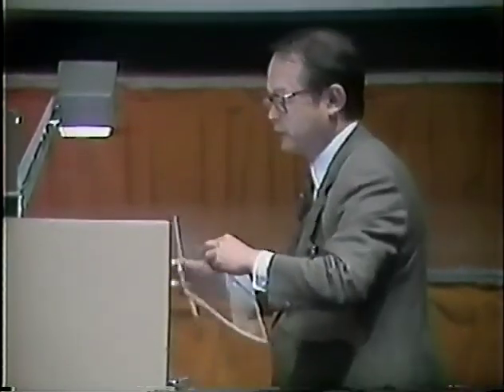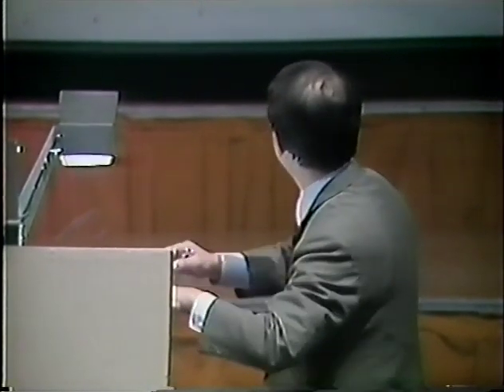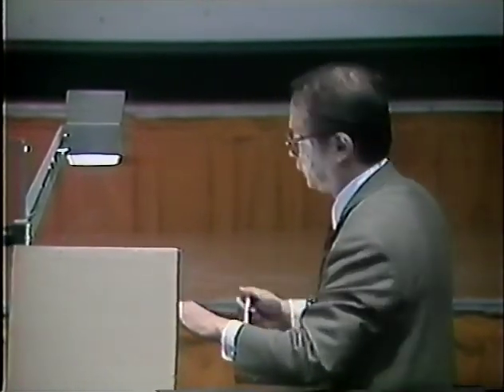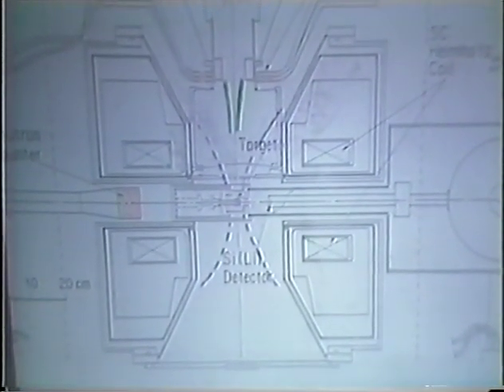At the end of the muon channel, we installed this setup. The muon is coming to the target area. At this moment, it's written on the D2T2 target, but it will be replaced by the palladium deuterium system. And we placed all the target under a high longitudinal magnetic field of 3.5 Tesla.